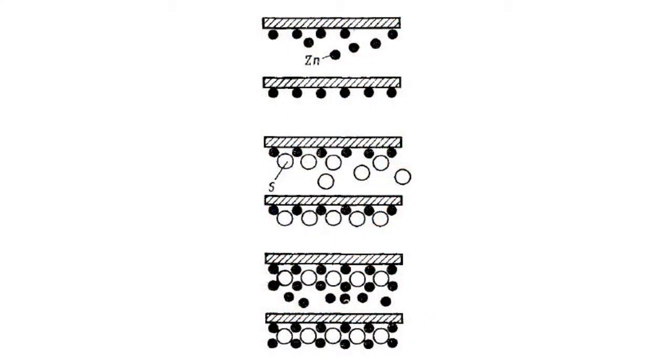Lighting and technical characteristics of emitters are determined above all by the type of luminophore used. Zinc sulphide can be used as luminophore. To get more brightness, it is activated by impurities of copper, manganese, or other elements. Zinc sulphide polycrystalline solids are linked to each other by dielectric materials. For this reason, powder electroluminescent emitters work only when there is AC voltage on electrodes.